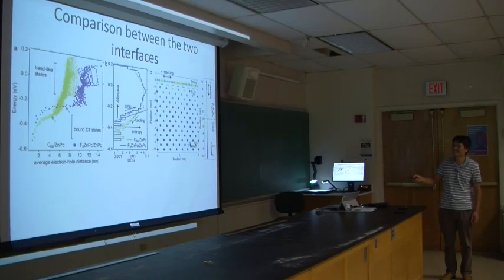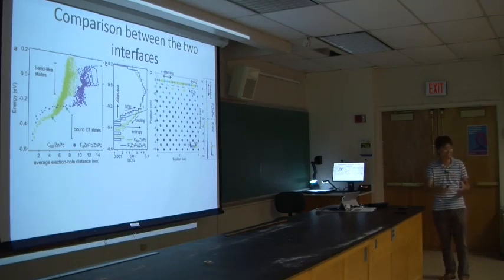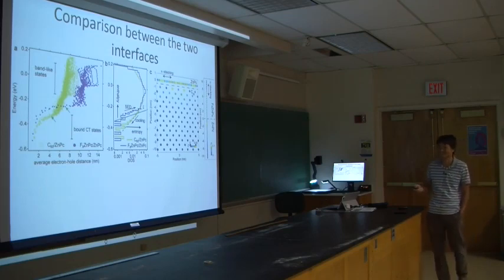So versus in that case, the electron and hole kind of fall to the interface due to the structure of the crystals, right? So your hole is always gliding parallel to the interface. That's why you could have more different combinations. You have your hole really close to the interface, and so there are many possibilities for this tightly bound state.